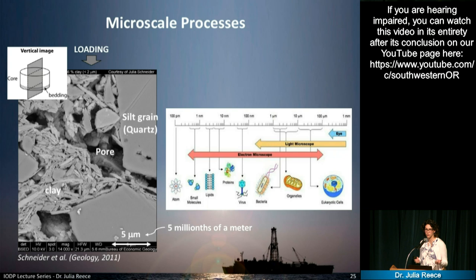And we have a scale here of 5 micrometers, so this is 5 millionths of a meter. And these are the silt grains, and these are the clay particles that are extremely small. But what we take away from this image is that if you have a significant concentration of these silt grains, these larger grains here, then you start to preserve a lot of pore space. And that's what you see here, what is a little bit darker outlined here. This is large pore space that is preserved in between these silt grains.